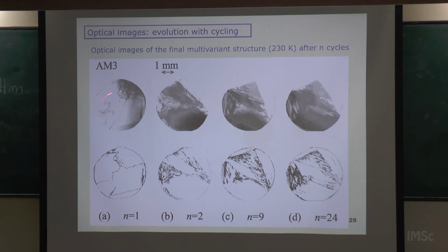This is just, first of all, optical images. These are old measurements, but okay, these are images of the surface of the sample after the transition. You see the transition is similar to the first image I showed, but for this sample you don't see it very well, but here I have marked the separations of the different coexisting martensitic domains. This is after the first loop, so you just cross the transition and you have this image. You see that there are big domains of different martensitic variants. Then you do a second loop, so you go up and down, and then you get many more domains here.